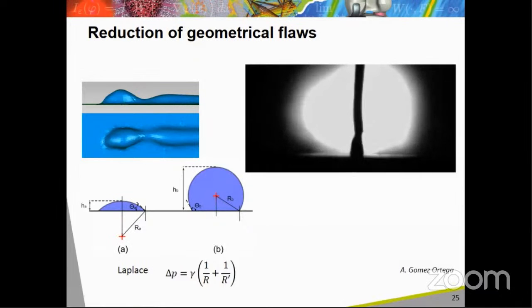The wetting of the liquid on a solid substrate is very bad at the beginning of a deposit, producing an increase of the curvature radius with the increase of the deposit height, and so a pressure decrease that promotes the further increase of the deposit height. We can see the newly deposited droplets are sucked towards the rear of the bed, forming a narrow area in the front of the deposit until the rear of the deposit solidifies and stops the phenomenon.